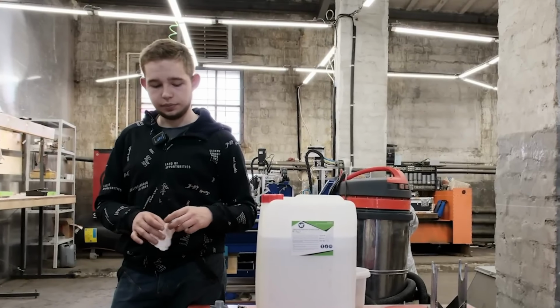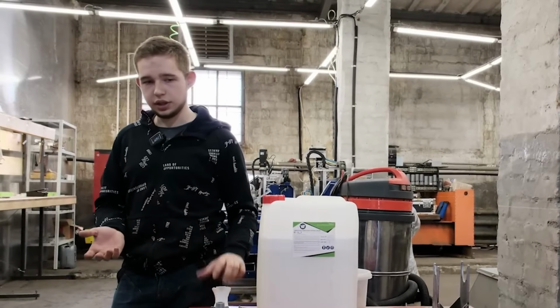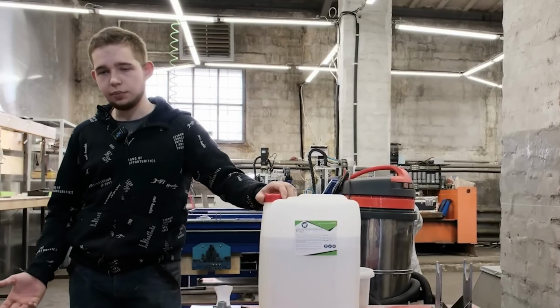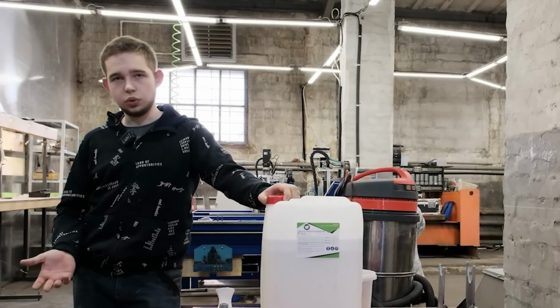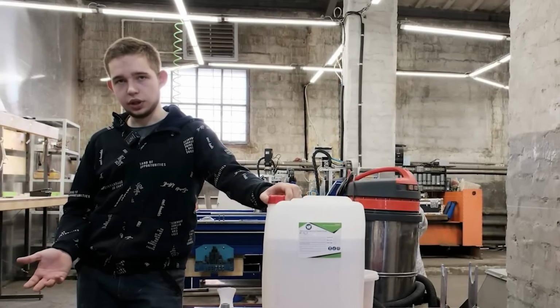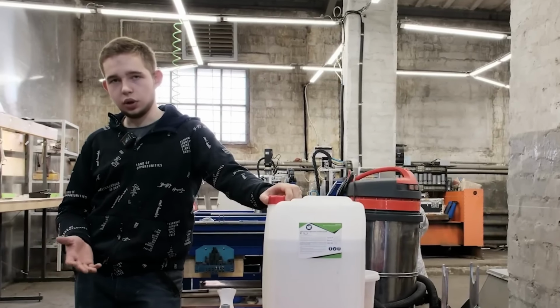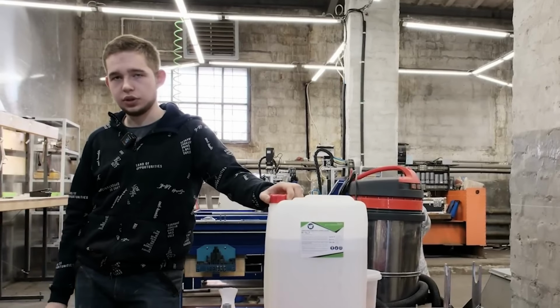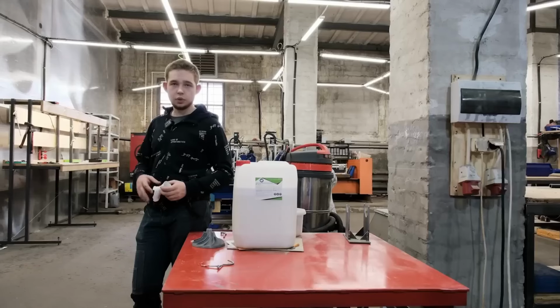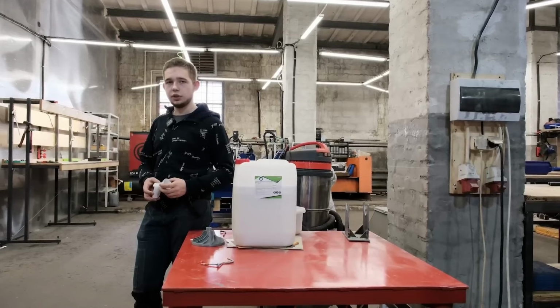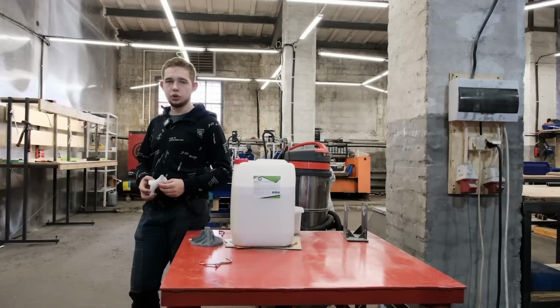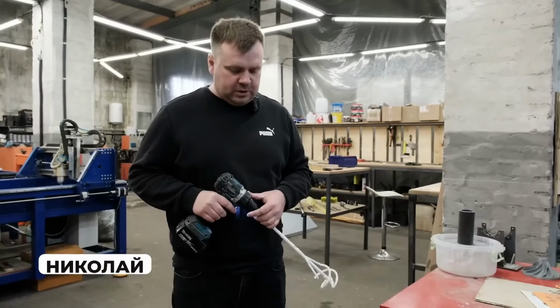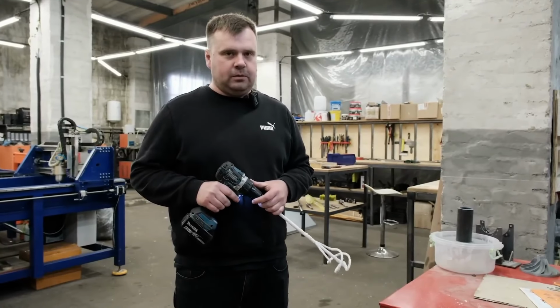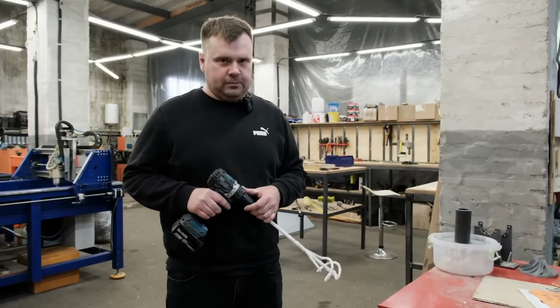We want to try making ceramics completely from silicon, meaning that as a filler material, we will use marshallite as the filler, and also quartz sand F40. Perhaps by using these proportions, the ceramic will be more stable against temperature fluctuations. So we're starting to carefully prepare the mixture for dipping our mold.